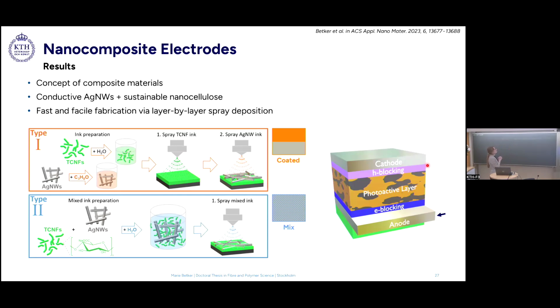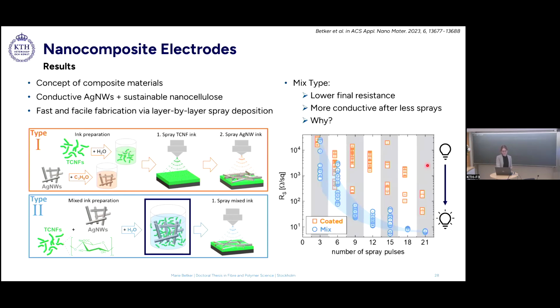And here again, we tested two different compositions. So on top, you have the orange or the coated type again. This is a two-step process. So here we first sprayed a layer of TCNF, and then we sprayed the nanowires on top. And the nanowires here were in isopropanol. In the other case, we directly took the TCNF and the nanowires, mixed them in water, and sprayed this mix directly. And here you can see the results.